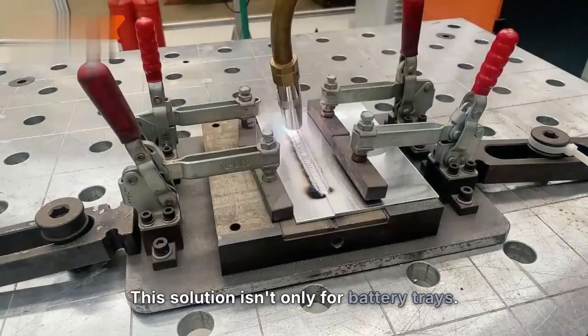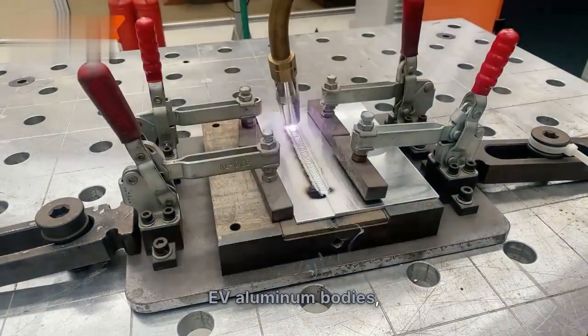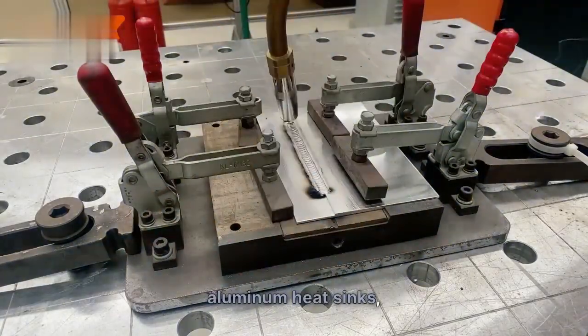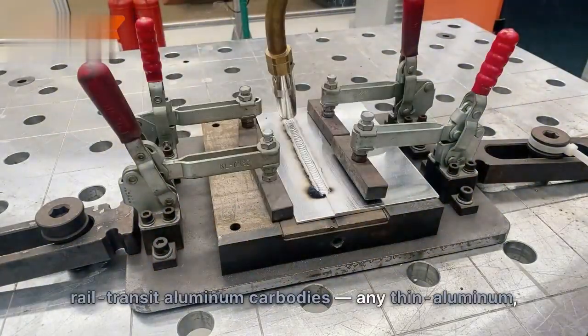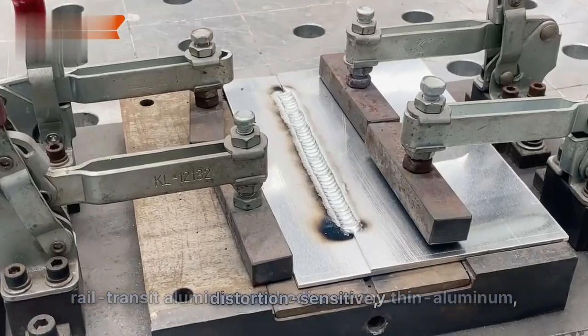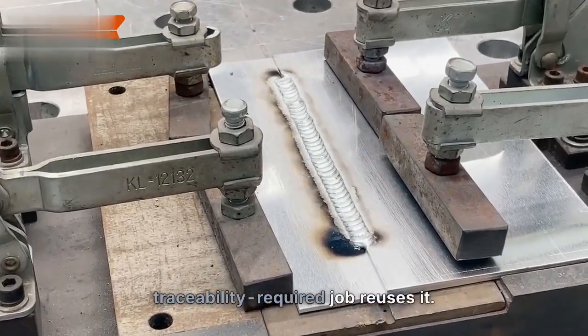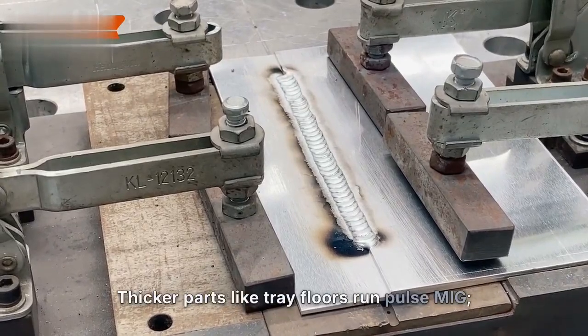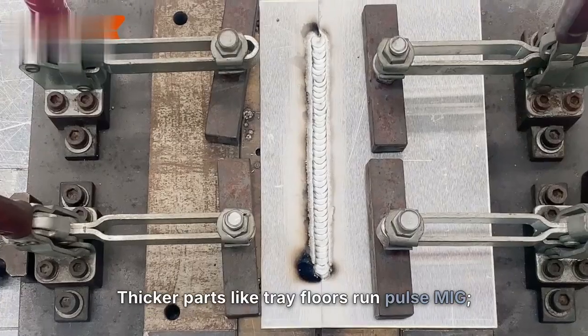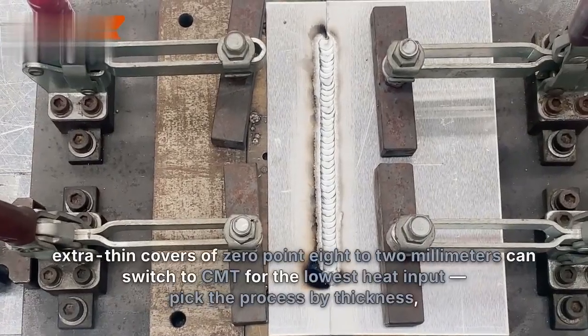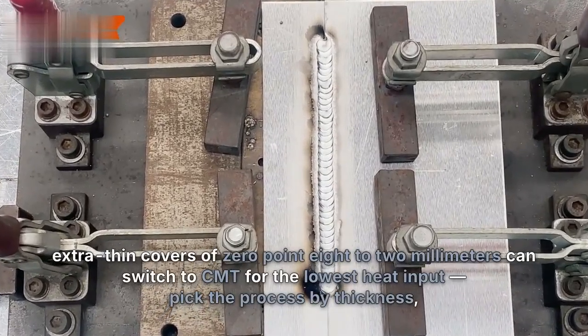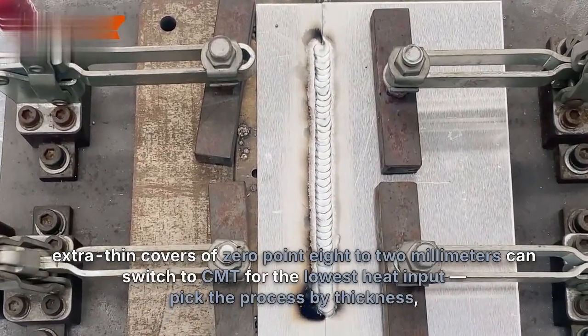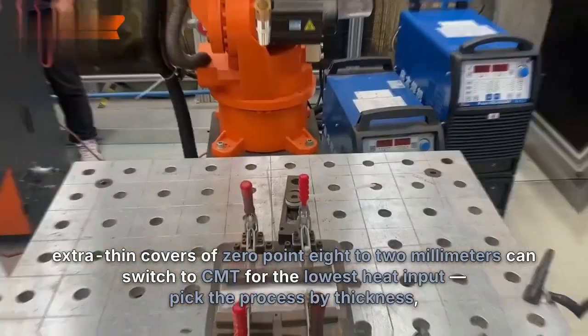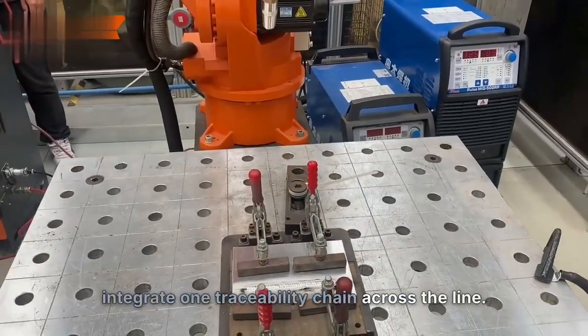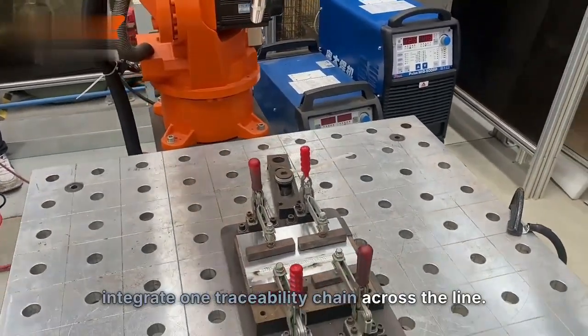This solution isn't only for battery trays. EV aluminum bodies, aluminum heat sinks, rail transit aluminum car bodies, any thin aluminum, distortion sensitive, traceability required job reuses it. Thicker parts like tray floors run pulse MIG. Extra thin covers of 0.8 to 2 mm can switch to CMT for the lowest heat input. Pick the process by thickness. Integrate one traceability chain across the line.